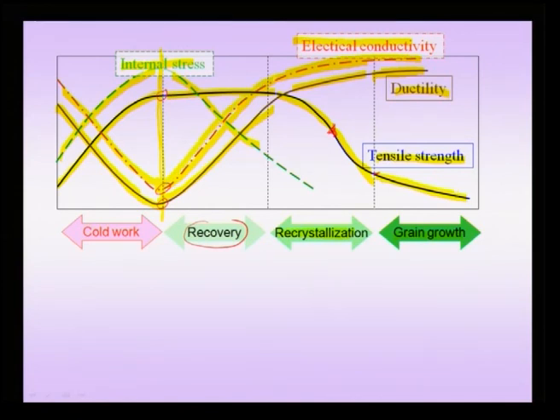That means that I do not have to wait for recrystallization, and this is because of the annihilation of point defects mostly, and therefore my lattice is less strained and I have a good amount of electrical conductivity. So microstructural transformations also lead to change in properties apart from phase transformation, which you have already seen can cause change in properties. Therefore, we have noted that if one is interested in engineering components, he can control the composition, but further he can engineer the microstructure